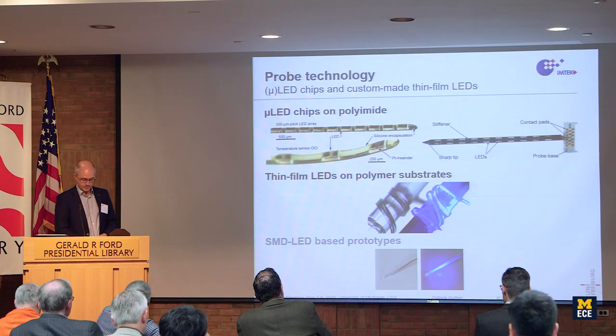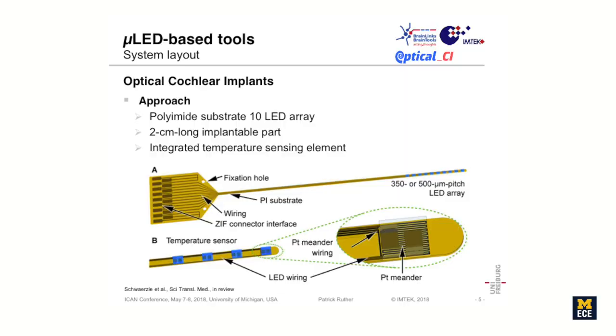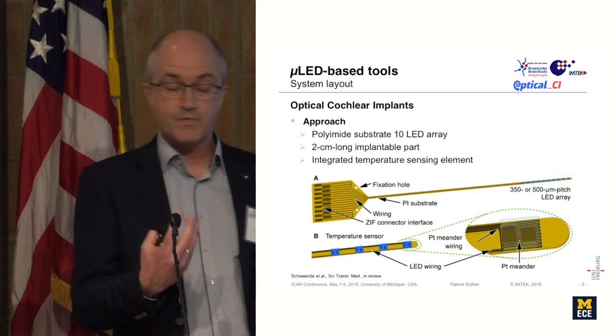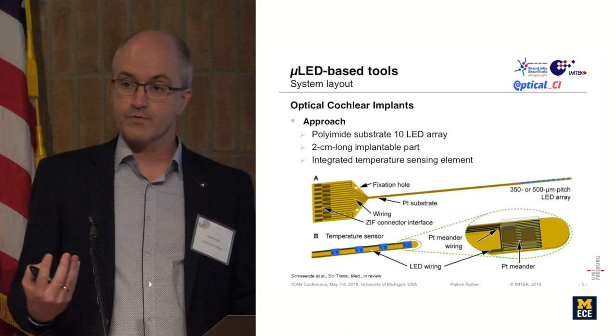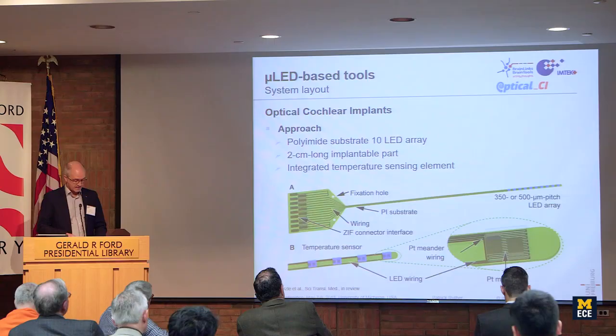Okay, coming to the first potential application of our flexible systems. This is the so-called optical cochlear implant substrate. So we have a long polyimide shank that carries 10 micro-LEDs. They might be equipped in addition with a platinum meander used for temperature measurements. And then for simplicity, we simply use an interface that goes into a zero insertion force connector, making a fast connection for our acute experiments that were done with these systems.